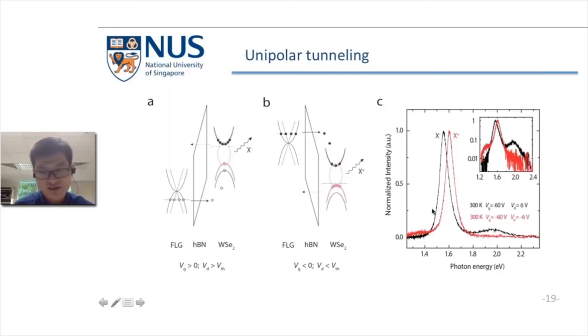Interestingly, we found that for negative trion, there is a hot trion emission corresponding with the valence band splitting due to spin-orbit coupling. This is because there is a possibility that the high energetic holes could recombine with the electrons. However, for the positive trion condition, there are no such hot holes, so we can only see a single peak.